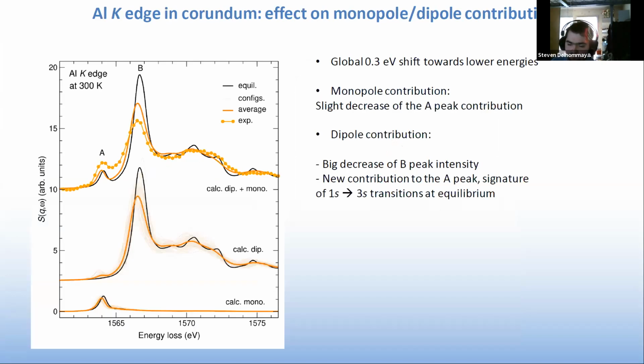So we remember that it allows us to check the monopole and the dipole transition channels, that is to say 1s to s transitions and 1s to p transitions. On the left, you have a comparison between calculation and experiment. So experiment is the dotted orange line here. And we have both the calculation using the QHA protocol, so what I described earlier, in dark orange, straight line, and the case for the equilibrium classical configuration, I would say, in a black line. And here it's a little bit hard to see, but I also displayed all the configurations for each of these contributions. And finally, we can see that I shifted vertically the different contributions. So here monopole, dipole, and the sum of both for more clarity.